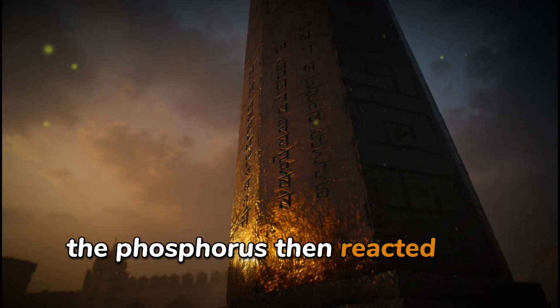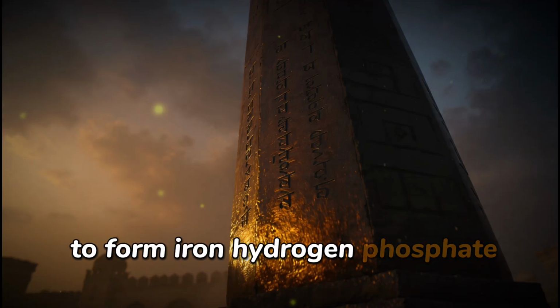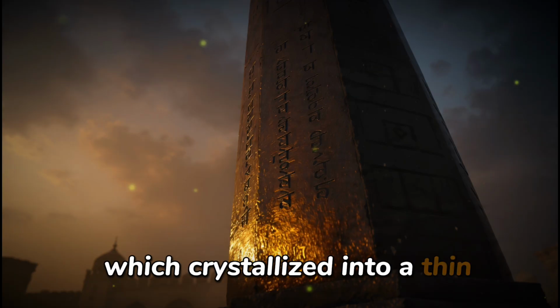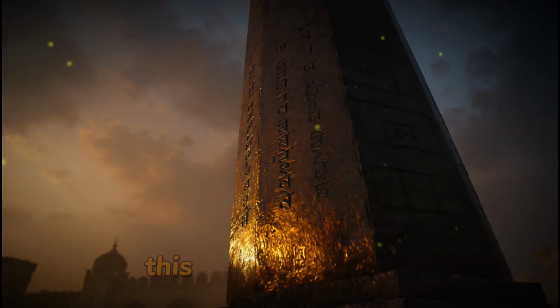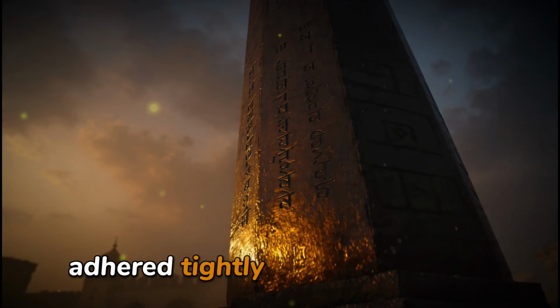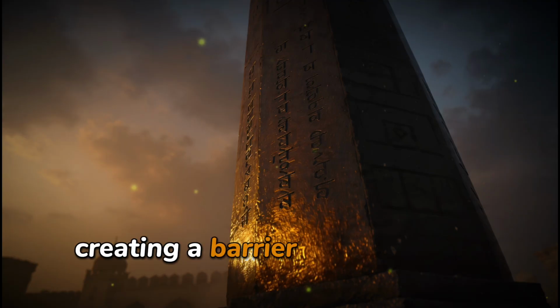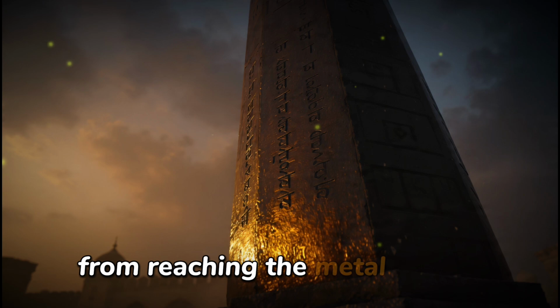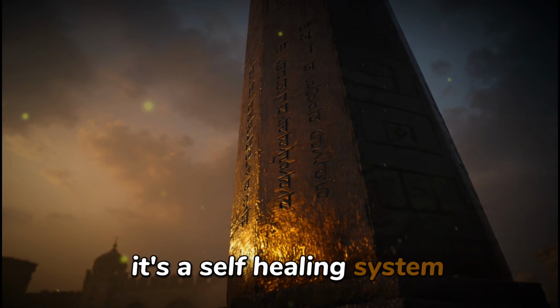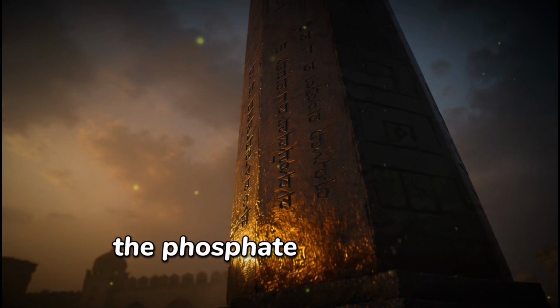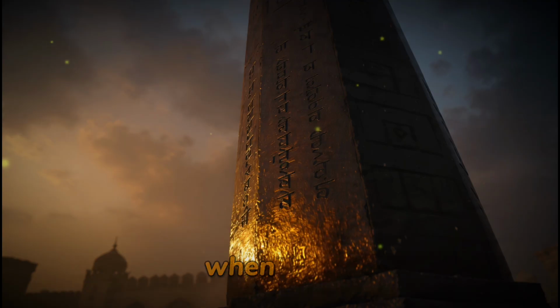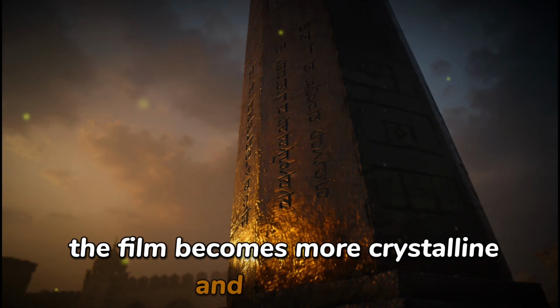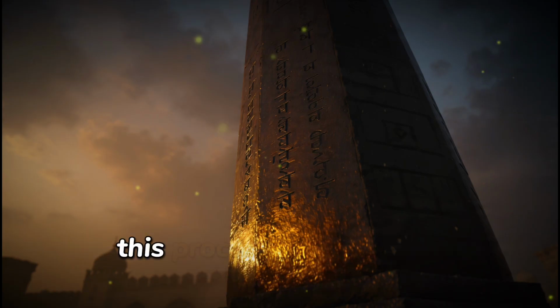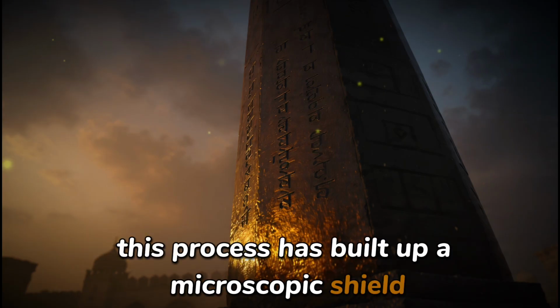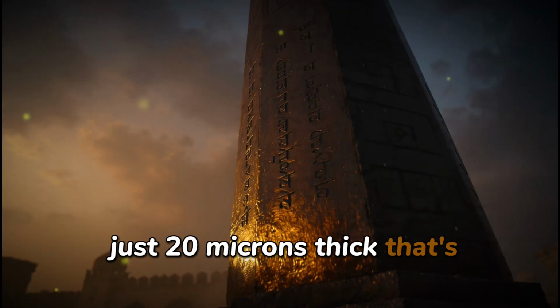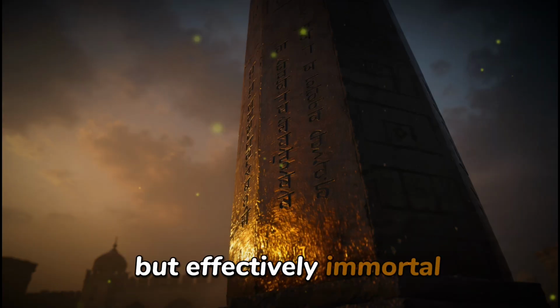The phosphorus then reacted with iron and oxygen to form iron hydrogen phosphate hydrate, which crystallized into a thin, dense protective layer. This layer, once formed, adhered tightly to the iron surface, creating a barrier that prevented moisture and oxygen from reaching the metal beneath. It's a self-healing system. When the pillar gets wet, the phosphate film slightly increases in thickness. When it dries, the film becomes more crystalline and protective. Over centuries, this process has built up a microscopic shield, just 20 microns thick. That's thinner than a human hair, but effectively immortal.